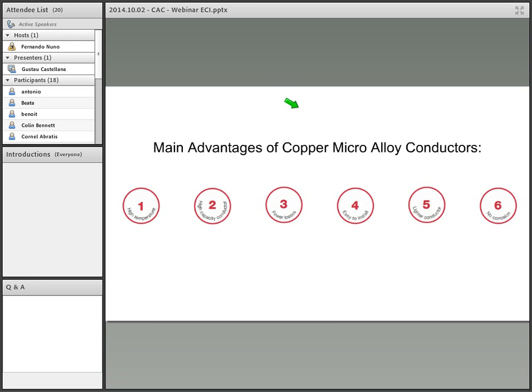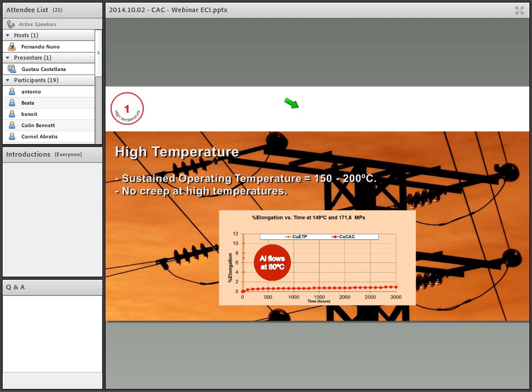So going through the first one, the first one is that this copper microalloy can work at high temperature. What does it mean? It means that, in a sustained mode, it can work between 150 and 200 degrees Celsius. And that's really important because even if we work at 200 degrees Celsius, there is no creep. And that's really an issue in the sector because once they are installing the ACSR, in some cases they have to come back to the line 30 minutes after or 1 day after and tension the conductor again to avoid problems of sag due to creep.